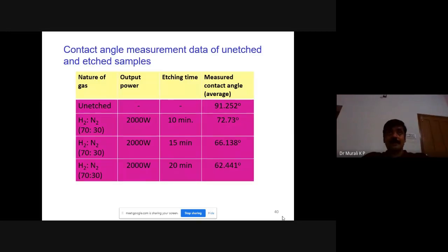Then how to clad once the surface is modified? Oxygen free copper sheet is available from the market. We can go for vacuum lamination. Take the temperature just above the melting point of the polymer, so that the top and bottom layer of the substrate get melted, and apply pressure with the oxygen free copper sheet so that it will adhere, or get fixed onto this dielectric part, and we will get the final substrate.